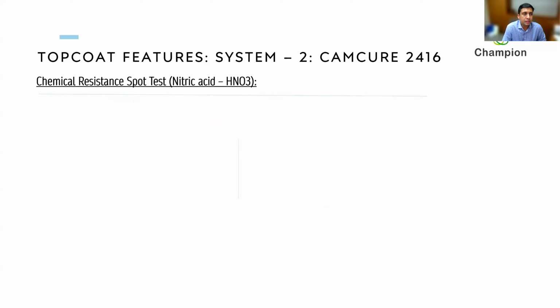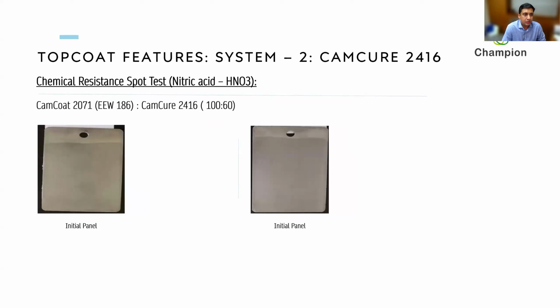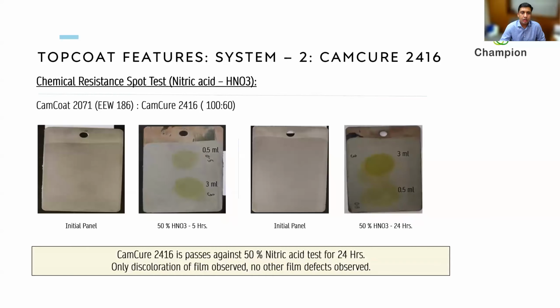I'll talk a little bit about the chemical resistance. We've checked chemical resistance for a lot of different chemicals, and that data is available with us for anyone who wants to know. Here I'm going to show some images for a few different tests that we've done. The first one is for nitric acid, which everyone knows is a very harsh acid. We've created panels on steel with a clear coat of basic liquid resin 2071 with CamCure 2416. You will notice that we have done the test at two different durations. The first one on the left is for 5 hours, and the second one on the right is for 24 hours. Even with 50% nitric acid concentration, you will observe that there is only minor discoloration in the film. There are no film defects or any kind of destruction on the film.